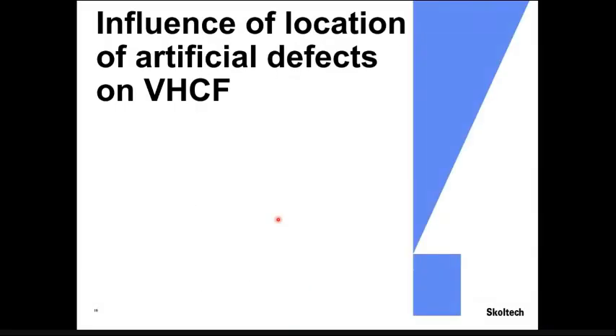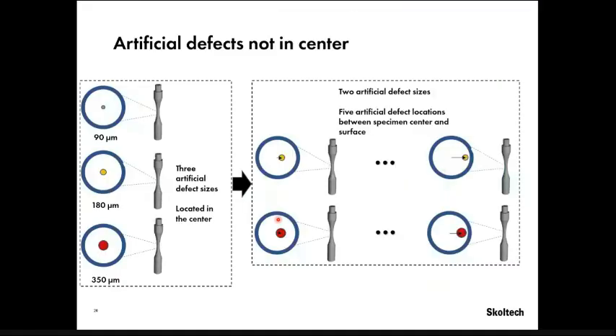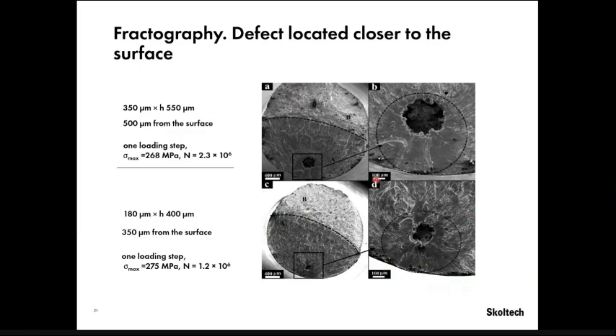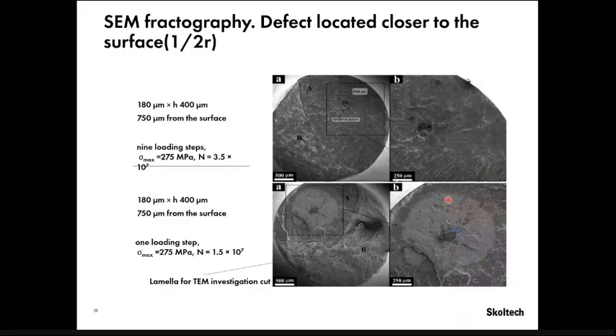And we started to shift our artificial defects closer to the surface, and we tested like 5 positions here, and we chose only 2 sizes. And we started to get crack initiation from the artificial defects when they are closer to the surface than previously. And you can see here like half a radius, but still in some cases, also at half a radius, we have this artificial defect here, but we have a crack initiation from closer to the surface.